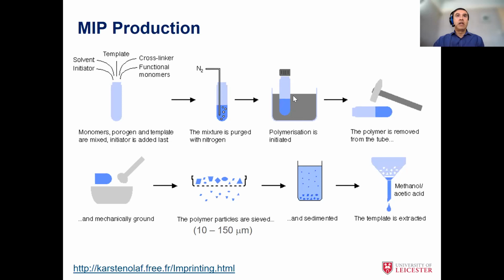You then seal it in a tube or a glass bottle, and you heat it up, you induce polymerization, you end up with a solid lump, which you can then get a hammer and smash if you want, and then you can sieve and grind and come up with a particle size of anything between 10 and 150 microns. So a little bit lighter than grains of salt, that kind of size. If you can keep that in your mind, that's really important.